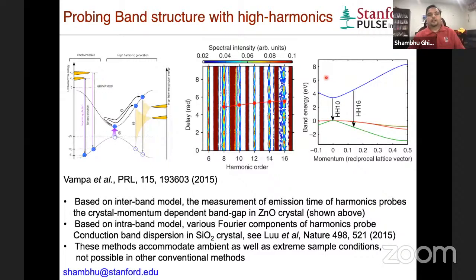This was exactly what was done by Giulio Vampa and his colleagues in this very nice example. Here they measured the emission time of harmonics from a zinc oxide, the same zinc oxide crystal. So this is the measurement data, and the idea here is as I described earlier. There are limitations. For example, this is the only range of energy that at least this spectrum provides. Nevertheless, this is a good gesture of the strength of the high harmonic generation process that could probe the band structure in the momentum space.